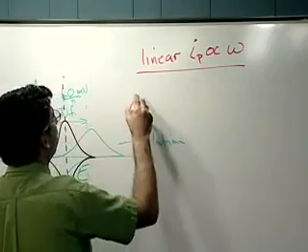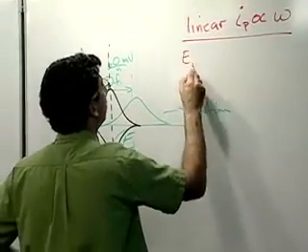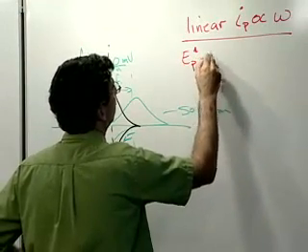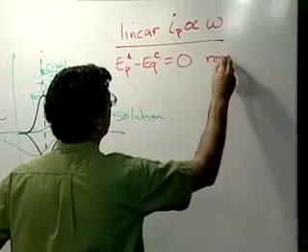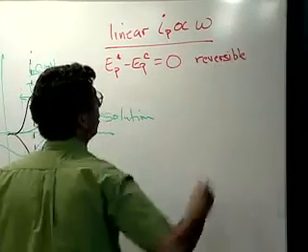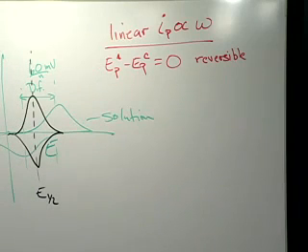We have now a peak anodic to peak cathodic separation that is equal to 0 for a reversible process. I should point out that although you can think of lots of different kinetic schemes, EC, CE, irreversible and whatnot, on an electrode surface, when you have a chemically modified electrode, it's the reversible one that is the interesting one, because with anything else, you only have a chemically modified surface for one cyclic voltammetric scan. And after that, you've converted it into something else. So we are specifically interested in the reversible case here. So not working out the other cases is OK.